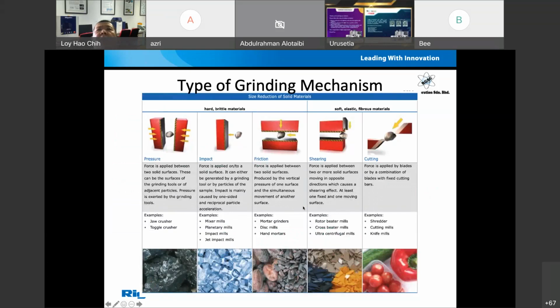Okay. So in terms of grinding mechanism, actually there are a few different ways to grind the samples, or to make the samples smaller. Okay, the first thing is by pressure. This is normally done using what we call a jaw crusher. When we have a very big chunk of rock, then we put it in a jaw crusher. It will crush it into a smaller size, something like less than 5 millimeters diameter, or less than 10 millimeters diameter. Then after that, we go for impact. So impact is normally something like planetary mills or mixer mills, where the samples will bang against the wall of the vessels, and as the process goes, the samples will get smaller.